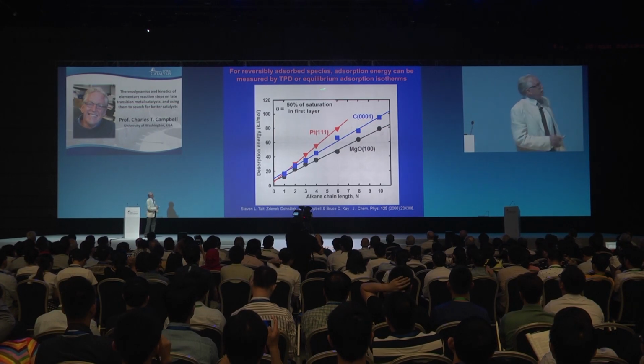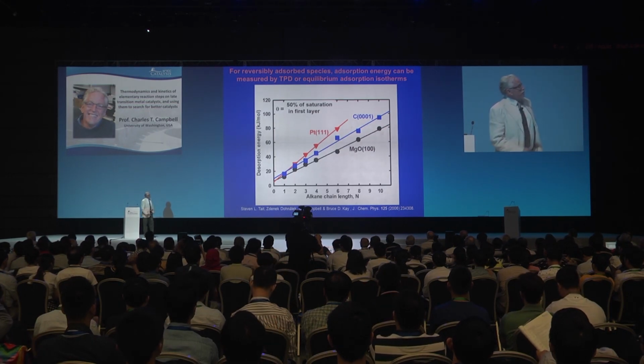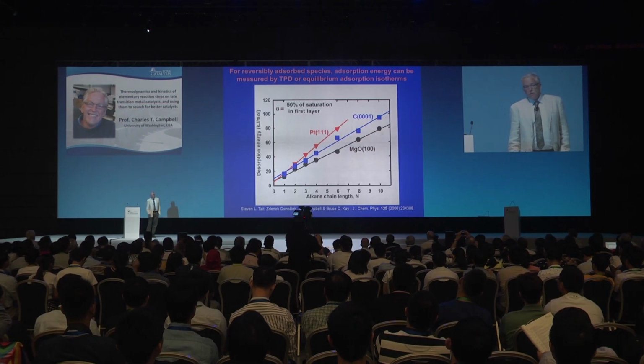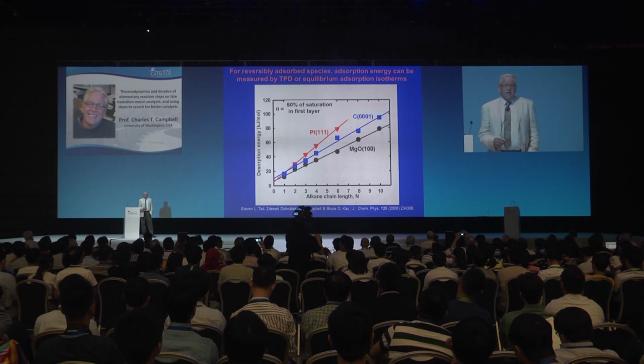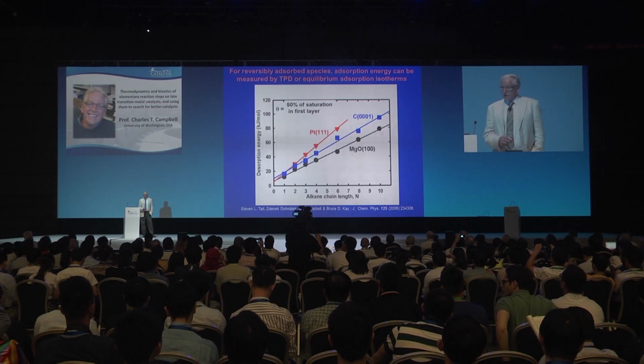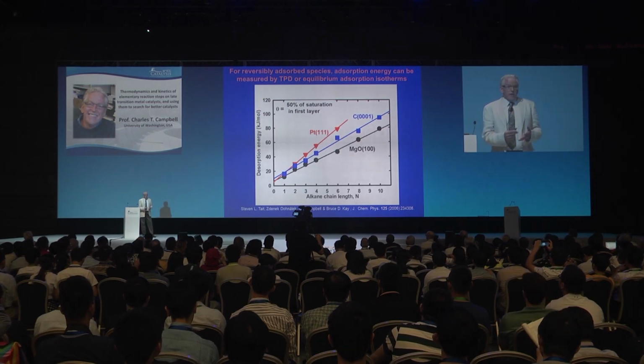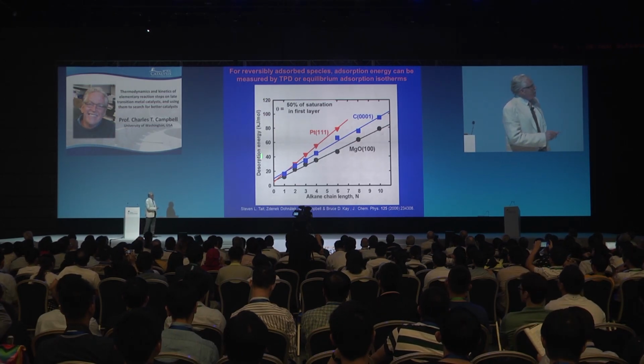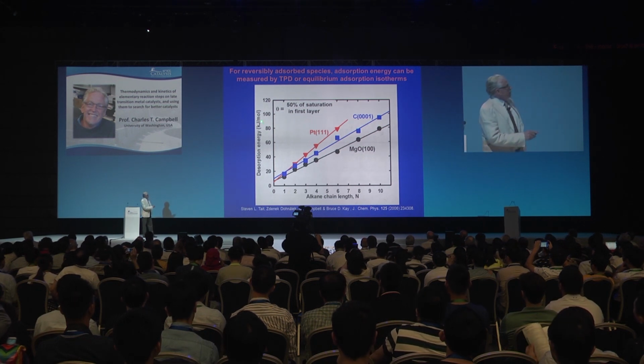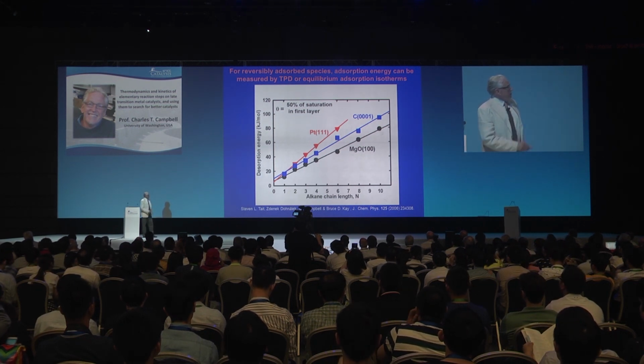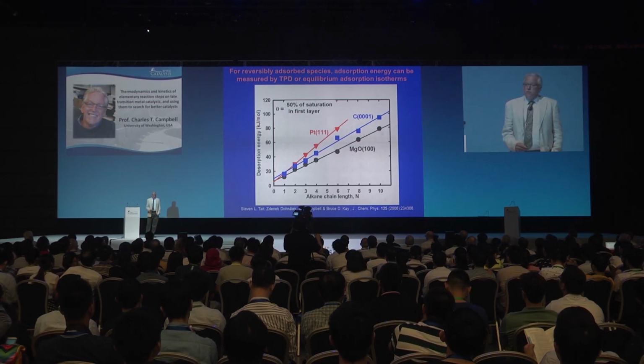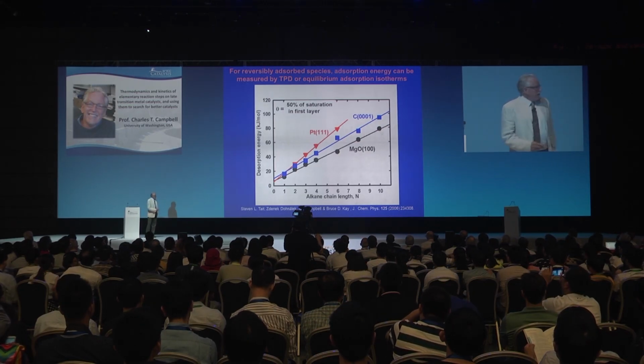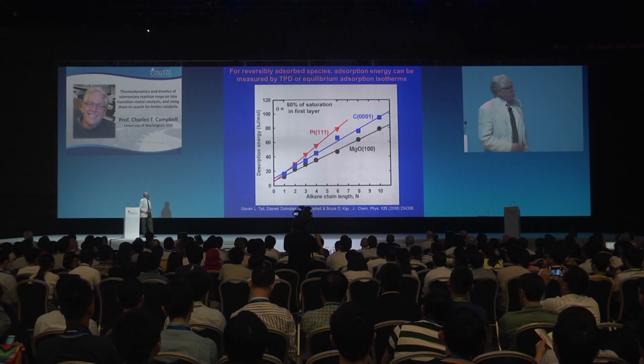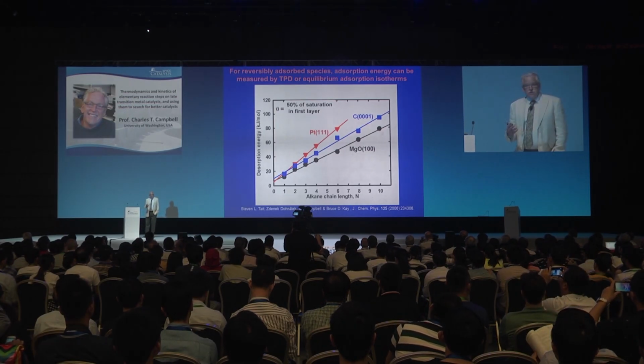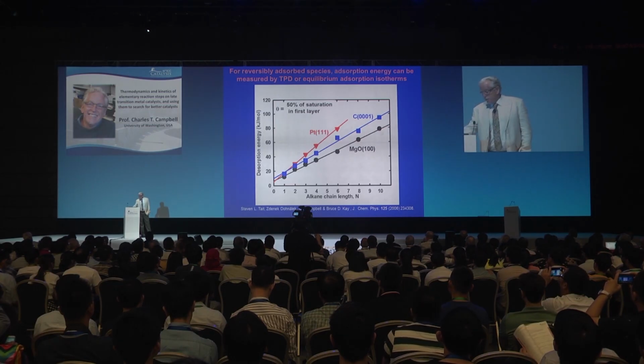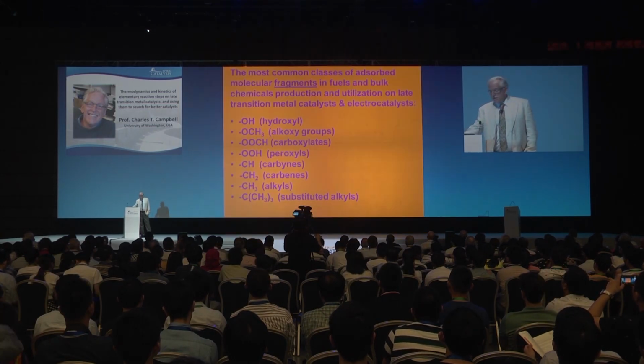And so those could be studied by temperature-programmed desorption and equilibrium adsorption isotherms, and those are known for many molecularly adsorbed species and a few dissociatively adsorbed species, like hydrogen and oxygen, that desorb again reversibly. Here are examples of temperature-programmed desorption measurements of the desorption activation energy, which is essentially equal to the adsorption energy, for a series of n-alkanes on different single crystal surfaces. So that technology for reversibly adsorbed species has been around for decades.